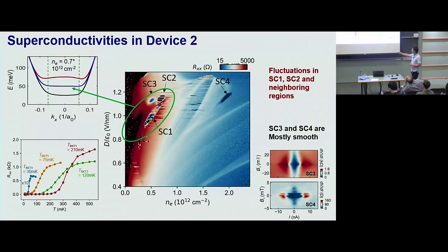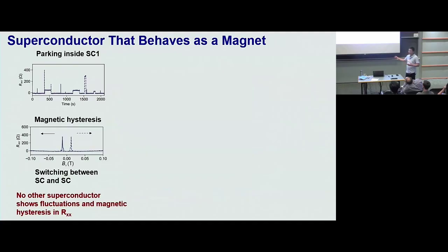It looks jumpy when you do this ND map. You scan the charge density at the fast axis. And it is still fluctuating if you park at a specific combination of the N and D. This is taken inside SC1. You just park there and you watch it as a function of time. You see, most of the time it stays at zero resistance, but from time to time you get a jump, right? A spike or a little plateau before it goes back. It is fluctuating. And there is magnetic hysteresis.